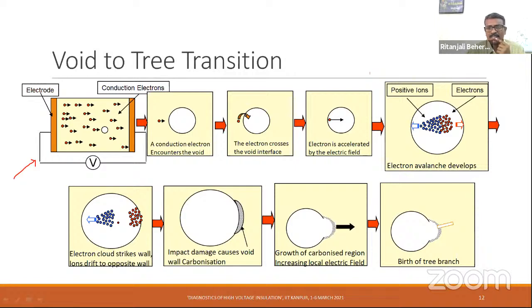And once a partial discharge takes place, it bridges the gap, something like this. It bridges the gap here. The potential difference between this end of the void and this end of the void becomes 0, and hence the discharge quenches by itself. And when the voltage goes up, this process repeats. So it is a repetitive process.